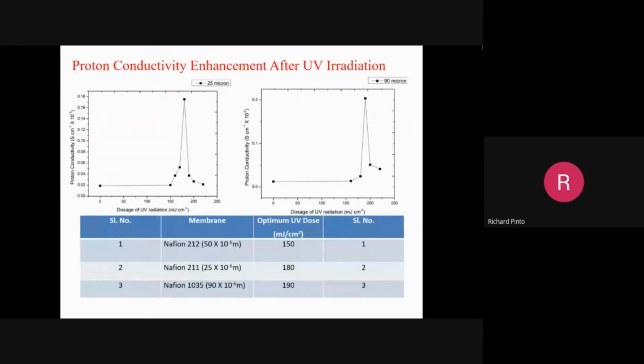Now what we have obtained is shown here. Proton conductivity enhancement after UV radiation. I explained this different plot for that, but this is work done with respect to the various membranes here. 212, 50 micron, 25 micron, 90 micron. Here we are not using the 183 micron membrane because it's too thick and the internal resistance is too high for HFC. And in HFC, hydrogen permeability is very, very small, negligible. So we don't have to worry about coating and so on. So the 183 micron membrane we didn't use. We use Nafion 212, that is 50 micron, Nafion 211, which is 25 micron, and Nafion 1035, which is 90 micron.